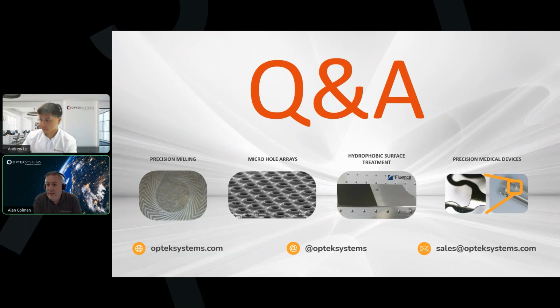Another question is, how thin can you make a micro hole array? Now, this question, they've said, I want to make a 30 micron hole with a thickness of less than 10 microns. So that's one of our specialties right there. We have a lot of experience with micro hole arrays, especially very close to those dimensions and tolerances. To answer the question on a bigger scope, typically the thicknesses that we really start to see challenges with are in excess of about 3 millimeters in thickness.